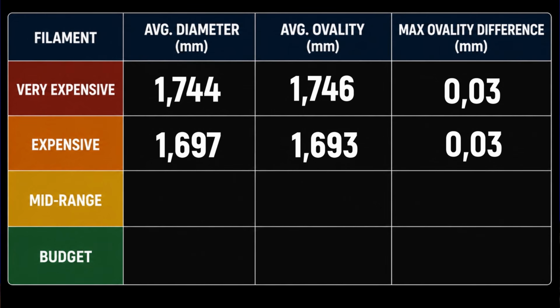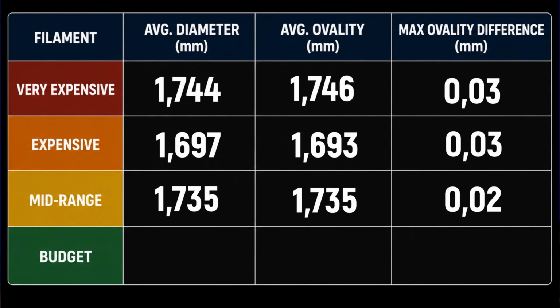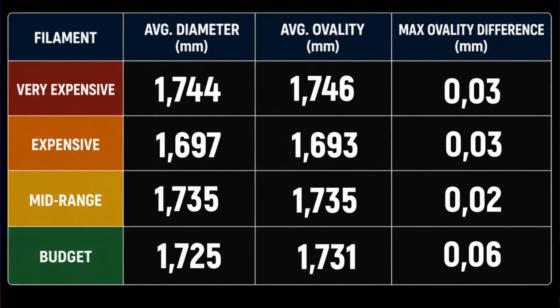When we look at the filament in the mid-price segment, the average value of measurements taken from 10 different spots was 1.735 millimeters. It also has the distinction of being the only filament whose ovality matches its diameter. The average ovality was also 1.735 millimeters, and the maximum difference between measurements taken from the same spot was 0.02 millimeters. For the cheap filament, the average diameter measured from 10 points was 1.725 millimeters, while the average ovality was 1.731 millimeters. The filament with the most measurement inconsistency in ovality measurements was the budget filament. Here the difference rose up to 0.06 millimeters.